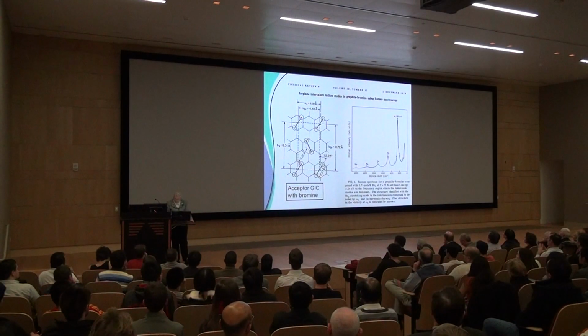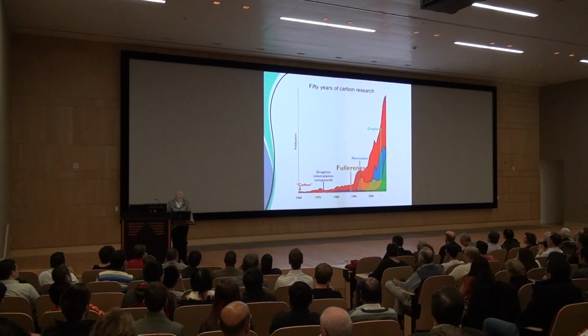And here are molecules that sit between the layers. These are bromine molecules. They stay in molecular form, but we can measure how they get changed by measuring some property. For example, the lattice vibration of the two bromine atoms in the molecule changes by about 50% when you put them between these layers. It's amazing that you can have such a big interaction and the molecule still stays together. That's one of the wonders of chemistry, that things like that can happen. And we were able to measure the spectrum here for many orders. As you can see, there were harmonics in the vibrations.